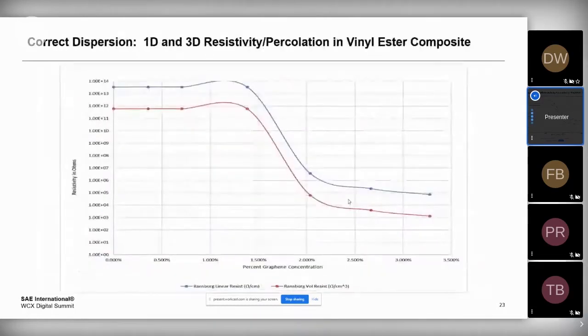So one more thing I'm going to mention in here, and that is that the dispersion characteristics will also impact your electrical conductivity. Here in this graph, I'm showing from 0 to 3.5% graphene. We're looking at two different types of conductivity. One is one-dimensional, point to point, and the other is three-dimensional in terms of volume. And we see that with a properly dispersed graphene dispersion, you can achieve a percolation on the order of 1 to 1.5% when you start to see a significant increase in electrical conductivity in a vinyl ester type composite.